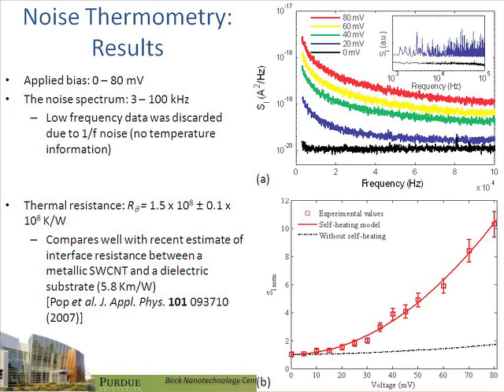If we had just used an isothermal model, the noise spectrum would look like this. But if we have a self-heating model, the red curve ensues, and you can see that our data fall right on top of that. So we were able to measure thermal resistance. That's the thing we added in order to go from different temperatures to understand how self-heating changed the temperature. As we changed current, we changed temperature.